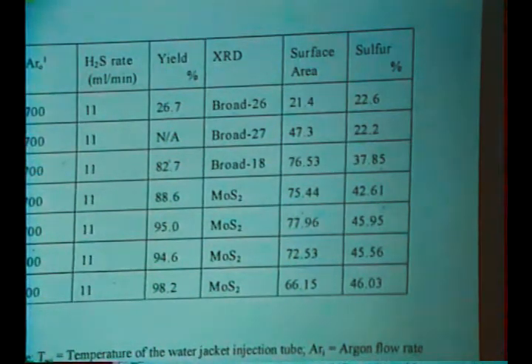Another thing you may want to take notice of is the sulfur concentration. The sulfur concentration at the lower temperatures is very low. For molybdenum disulfide, 40.06 is the sulfur amount. As you go from 400 degrees to 500 degrees, it takes a fairly substantial leap to produce a material that is close to that of molybdenum disulfide. And so for these compounds, somewhere between 400 and 500 degrees, we're seeing a transition from a molybdenum carbonyl, probably an oxycarbonyl sulfide, to moly disulfide.